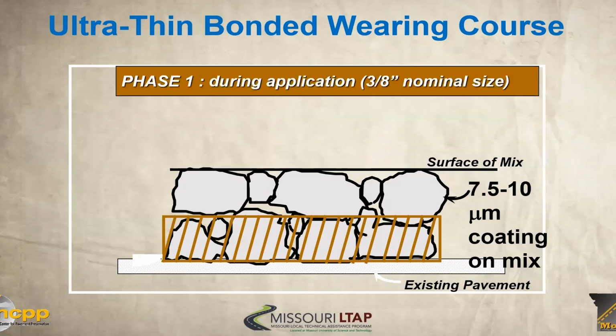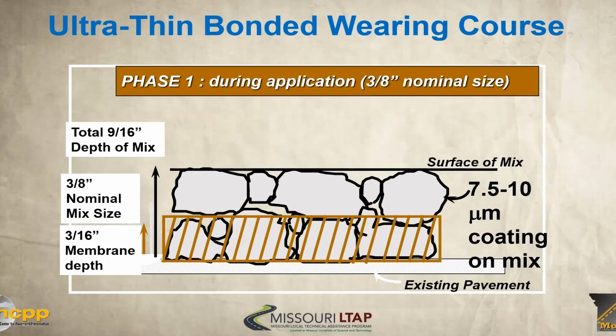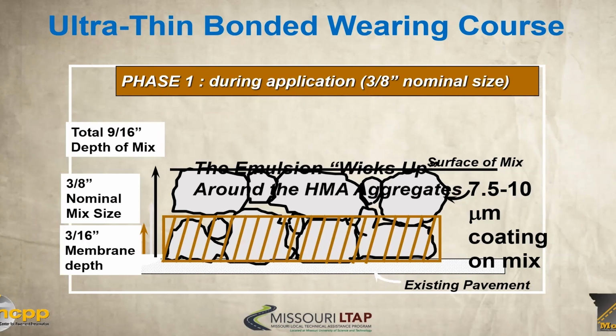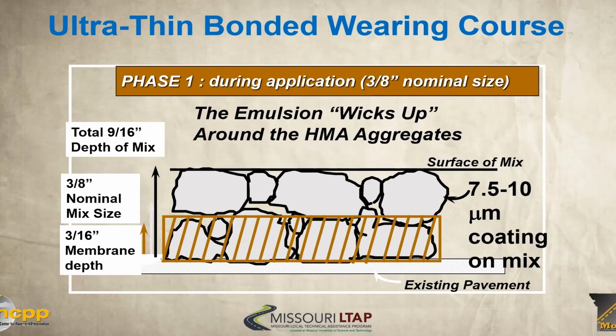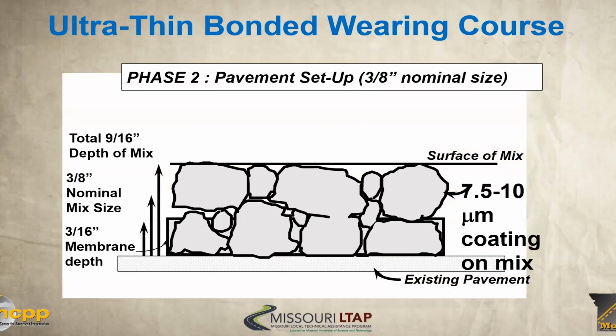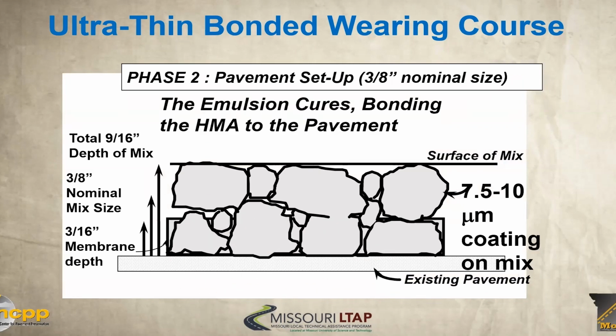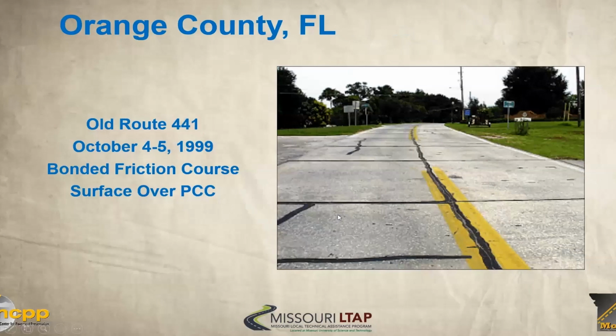So here's a little slide on that. You can see the membrane, the nominal mix size, and the total depth of a standard mix. And that emulsion wicks up around those aggregates. And because you have greater micron coating on the aggregate, it's going to extend the life of the asphalt overlay. And here you have it again. So you can see now, it should be black, but this little section here is now cured and adhering to the existing pavement. Now, this is a project that I was on back in the early days.